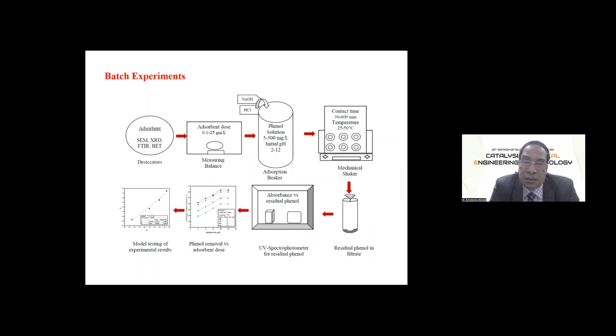So this is the batch study you can see here. First, we have taken the phenol solutions in a beaker. The ppm varies from 5 to 500, and with the addition of sodium hydroxide and HCl, the pH varied from 2 to 12. And whatever quantity of adsorbent dose will be required to go to the equilibrium stage, before that also we will have variations of dose, and for that we will be taking the adsorbent dose measured in a measuring balance. And then this beaker will be placed in a mechanical shaker where time and temperature will be maintained. Temperature will be maintained from 25 to 50 degrees centigrade and time 30 to 600 minutes. And within this time period, we will see that equilibrium has taken place. Then we will filter it, and the filtrate will be used in a UV spectrophotometer for measuring its absorbance, and through the calibration chart we will get the residual phenol concentration after separation of phenol in the adsorption process.